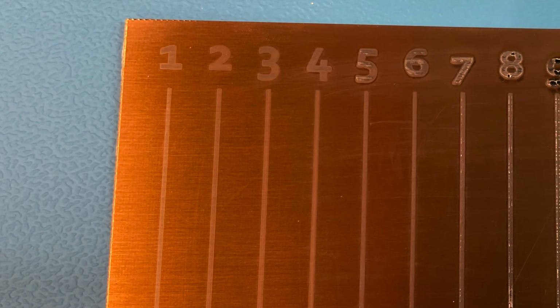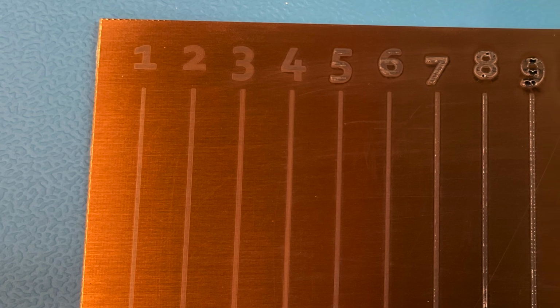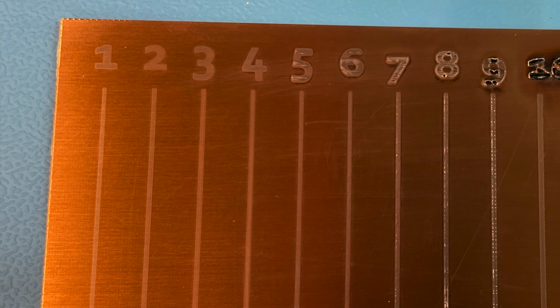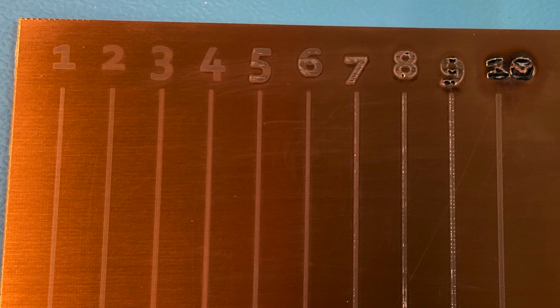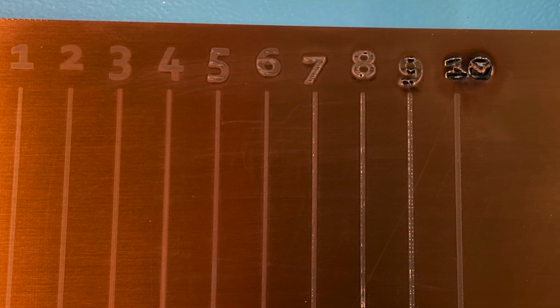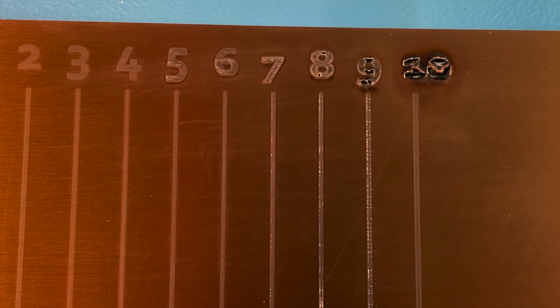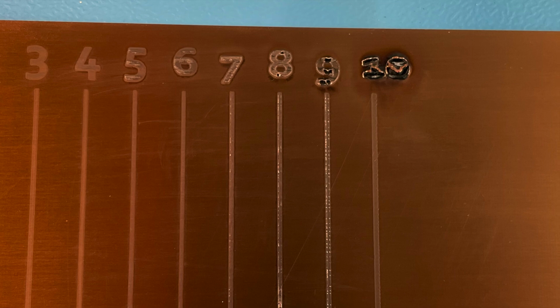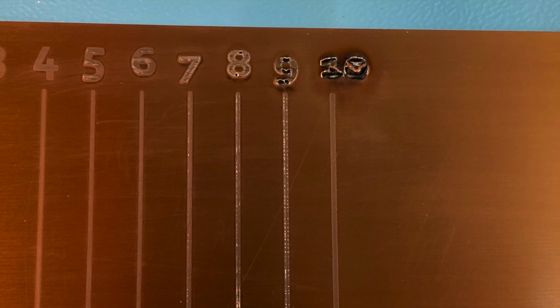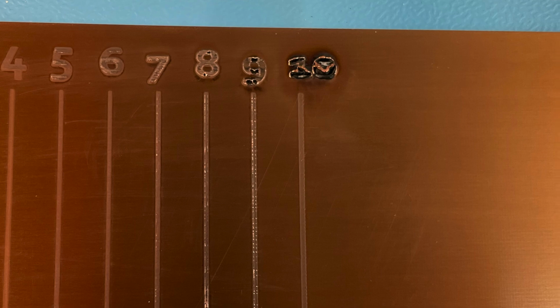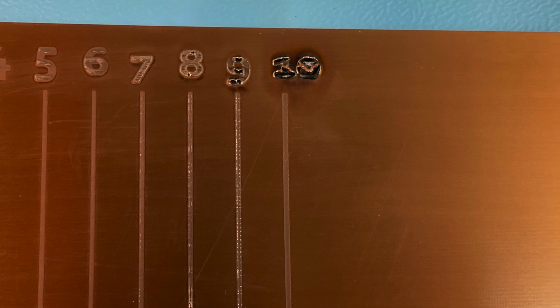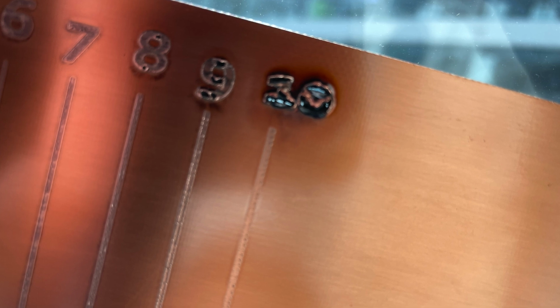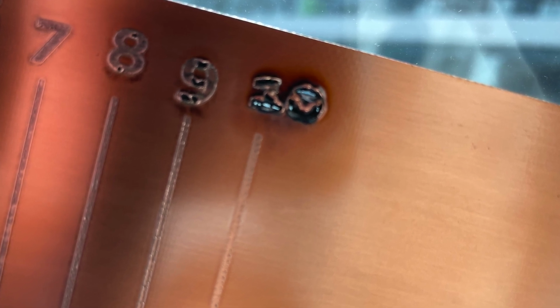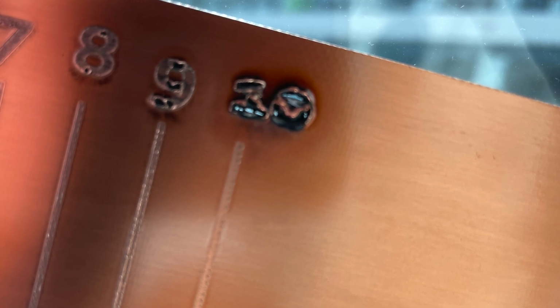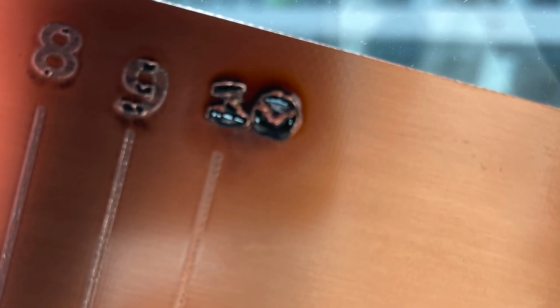Here we can see the results of the lasering process. We can see already here the lines and the numbers in the coating. It's actually not the copper, it's the coating itself that's changing color. We can see from the beginning until 4 or 5 that we have only the coating affected. But from level 5, 6, and 7 on, we are more and more damaging the actual copper already. So we're actually doing a bit more than we are attempting to. What we can see here is that at number 10, we actually melted through the whole circuit board. So not just the coating, also the copper on the top, the copper on the bottom, and the core in between, which is actually fiberglass and epoxy.